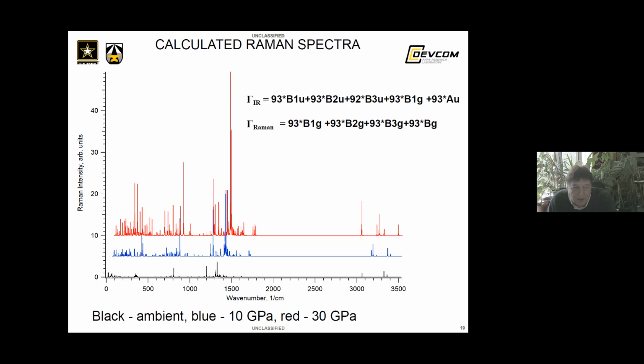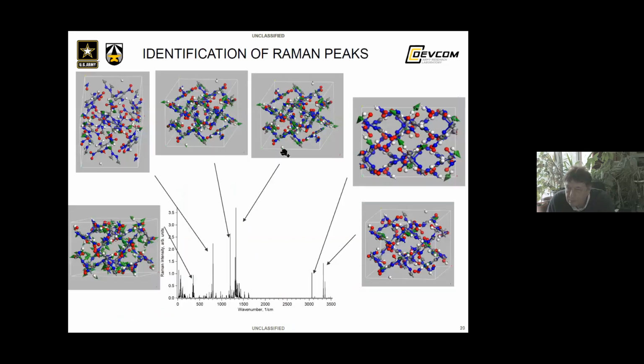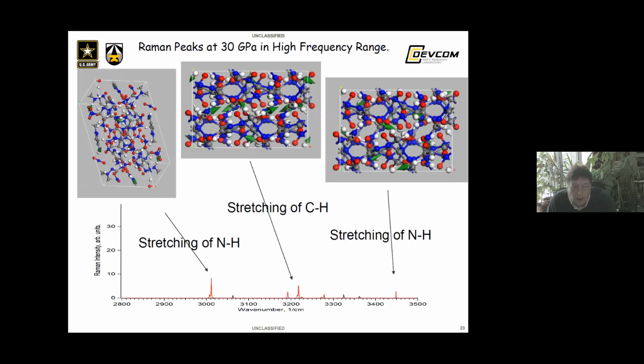There is a central symmetry in the lattice, and as a consequence, Raman active modes are not IR active. All peaks were identified in terms of atomic movements based on the dynamical matrix. Again, low frequency modes are related with complex collective modes, whilst in the high frequency region, the Raman peaks are related mainly with stretching of CH and NH bonds.